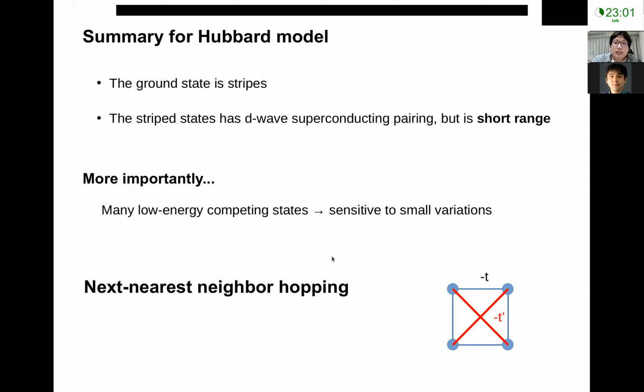So if we add additional terms that could be relevant in the experiment, it's very likely that the ground state will change its property, and maybe change to a superconducting state, consistent with experiment. So the next step is to consider an additional term in the model, usually the most important term being the next nearest neighbor hopping T-prime, which is a cross hopping. So now the electron can not only hop in the square lattice, but can also hop in this diagonal direction.